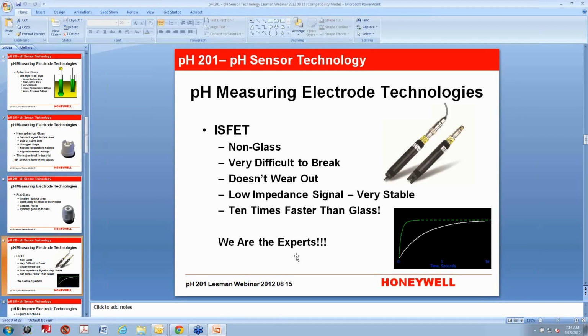A FET doesn't have a set of active sites that are being used up by hydrogen ions. It's actually creating a field, and it counts hydrogen ions coming through a gate in that field. So it's not going to wear out. It can be damaged by some process fluids, but when you get in the middle range, I would say that you're probably in pretty good shape of not having it damaged.